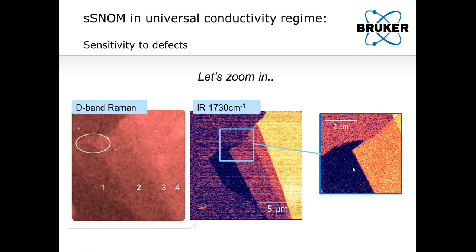So if we perform some statistics on that, we can actually show that the signal from that region is lower, indicating a lower amount of conductivity, which is what you would expect if you had a larger amount of defects there. And we can get to the origin of these defects by performing some nanomechanical measurements as well on the same region.